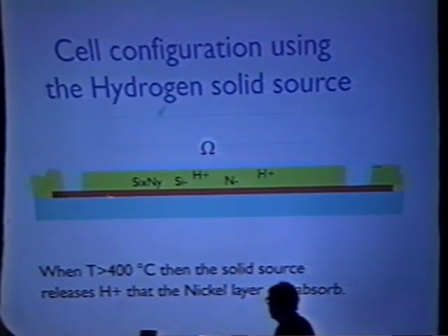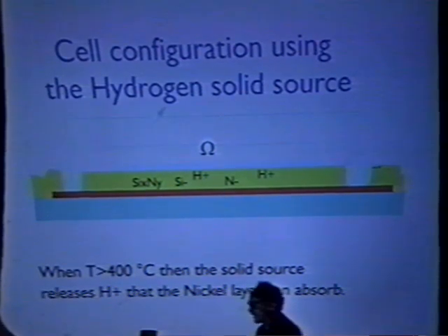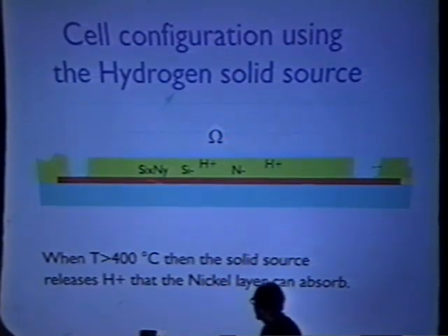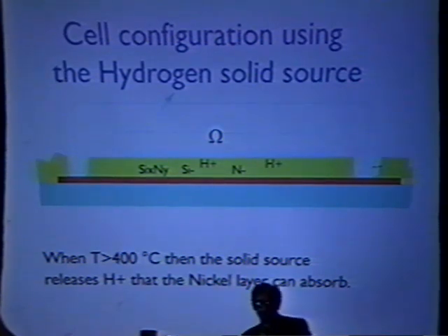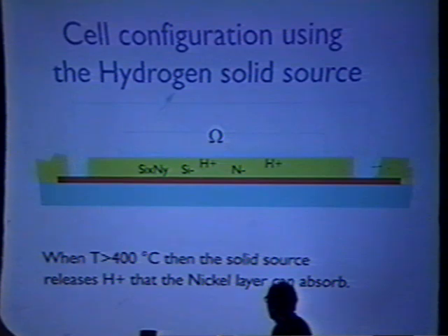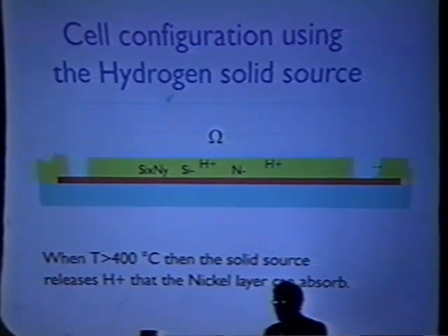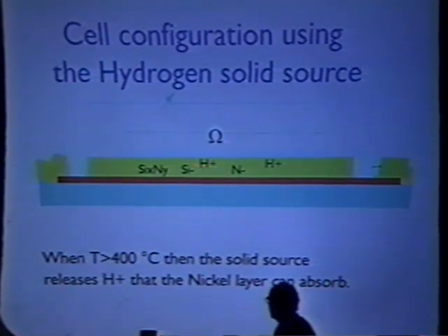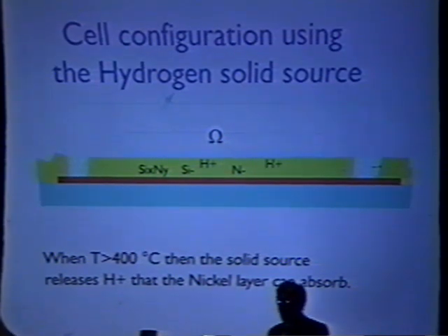But you can see here that you can bias that cell in many ways. So you can put some electric field inside this layer just to push hydrogen into the nickel. I used in my experiments sometimes this configuration. And also you can bias the nickel resistance and use that resistance as a heater too. As I told before, this layer was deposited at 350. So going up with respect to that temperature, you can have a release of hydrogen from that layer. Also, this fact is well known in literature, and the activation energy of this mechanism is a little bit below 1 electron volt.